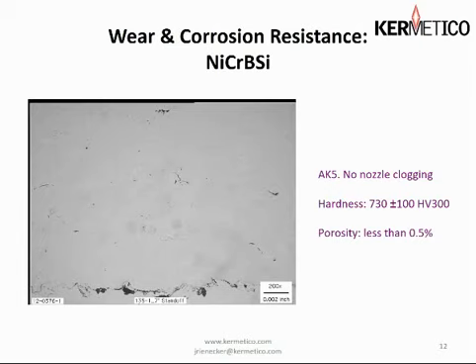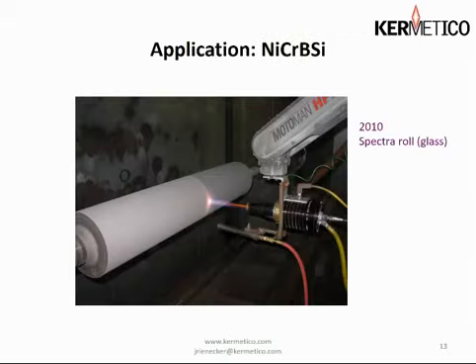This is nickel chrome boron silicon sprayed with an AK5, with no nozzle clogging. We got 730 out of it on a Vickers scale, and the porosity was less than 0.5%. Again, a very clean looking coating. Little junk at the interface, but nothing that causes any serious problems. And here we are spraying it on a Spectra roll in the glass industry.